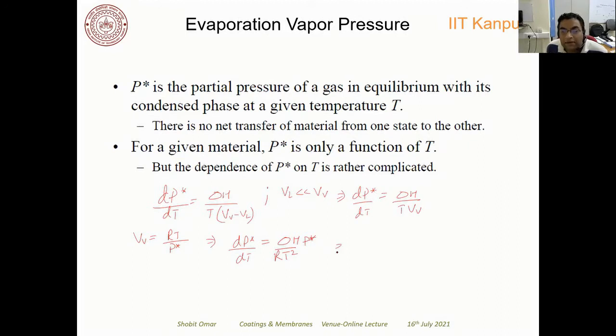Okay. Now you can integrate this here. What you will get is log P star equal to minus delta H by RT plus a constant C1. Now assume that C1 is a constant which is given by log C, where C is also a constant. So the relationship that you will get is P star equal to C exponential of minus delta H by RT. So this is how P star, which is the vapor pressure, is dependent on temperature.